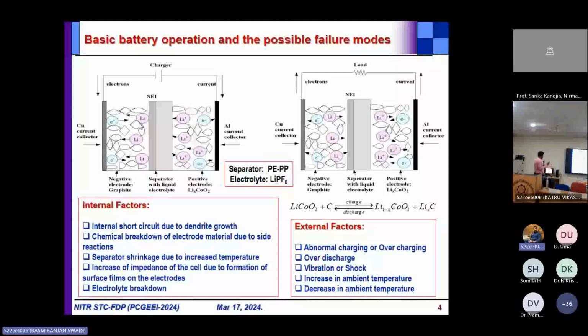Now what happens when the lithium ions penetrate through the separator from the cathode to the anode, if you repeatedly charge and discharge the battery? This is actually the discharging phase that has been shown here. Here, instead of a charger, there is a load connected, so the movement of the lithium ions will be in the opposite direction. Due to this repeated mechanism, on the anode surface there will be decomposition of active material from the electrode, repeated breakdown of active material, and deposition of layers on the anode surface, which is typically known in the literature as the solid electrolyte interface layer, abbreviated as SEI.